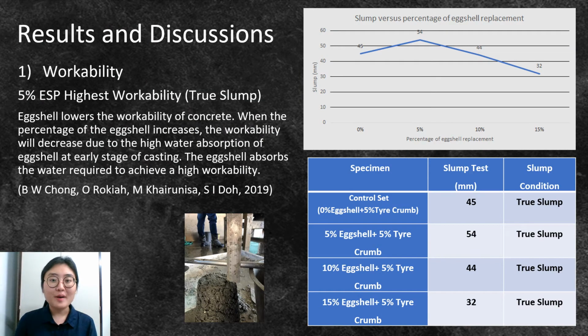This leads me to my next point, the results of my research. For the workability test, 5% of eggshell replacement achieved the highest workability, which is 54 mm with a true slump. However, the workability decreases after reaching the optimum eggshell content. From past research done in 2019, this proves the statement that increasing eggshell above the optimum eggshell content will reduce the workability of the concrete.